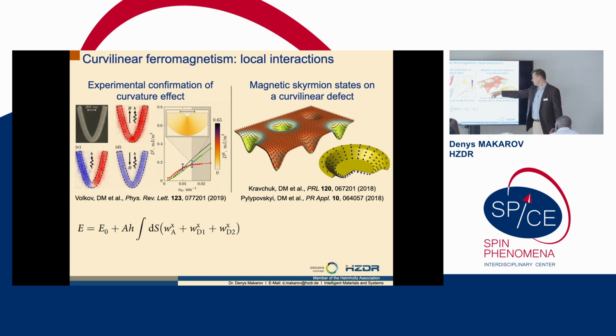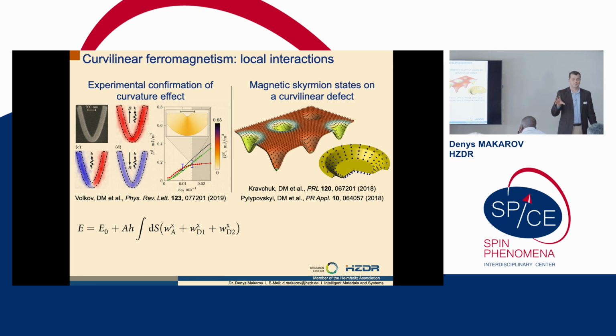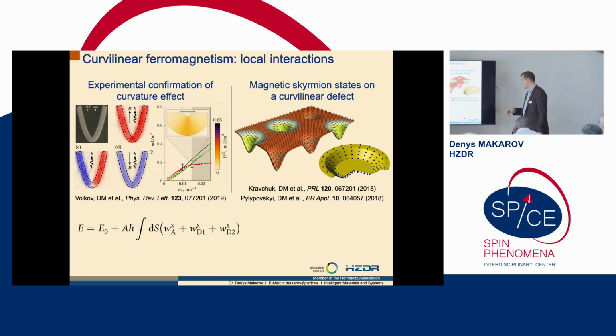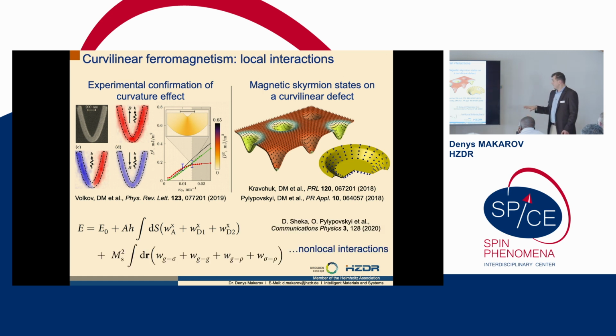You can have very high curvature, so here you will have really a skyrmion, as you know, a skyrmion in a simple permalloy film or cobalt platinum film without DMI, with a symmetric stack. Yeah? So a symmetric stack will give you a very standard skyrmion without any Dzyaloshinskii-Moriya interaction. So if you know that, everything else becomes very simple. There are a lot of things which are related to local interactions, because this is all about local interactions, and everything related to skyrmions, domain walls, you can already start understanding.